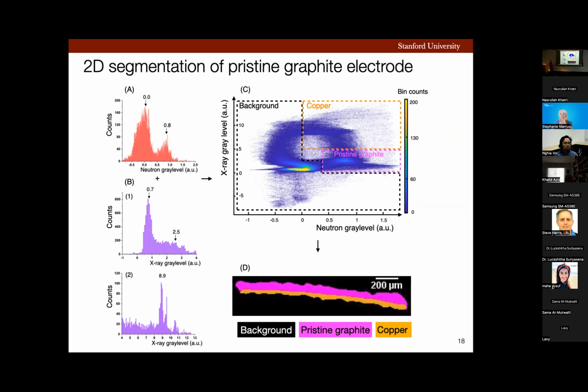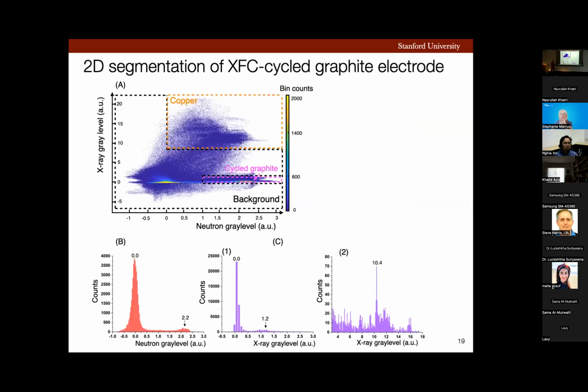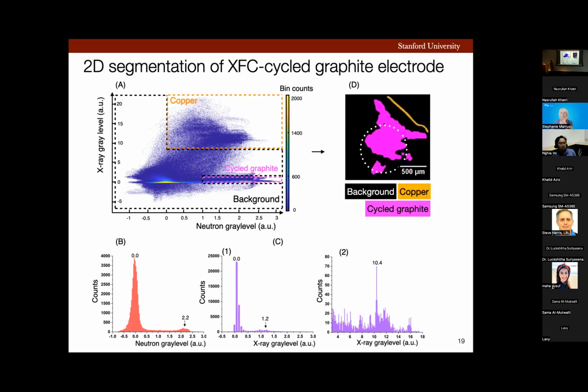Next, I used the same developed framework to segment different battery materials in my XFC cycled anode. Here, I used data from my neutron histogram and my X-ray histograms at the bottom of the slide to identify these materials in this 2D bivariate histogram, where background pixels were assigned and then copper and cycled graphite. Now let's look at the colorized image of the XFC cycled graphite, where you can see delamination of the copper current collector from the cycled graphite. We can also see this giant lithium-containing protrusion evidently beneath this white dotted circle.